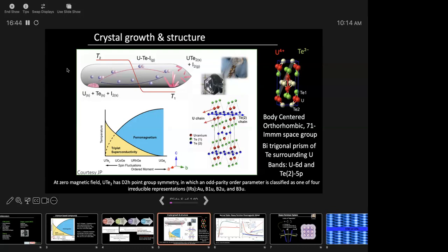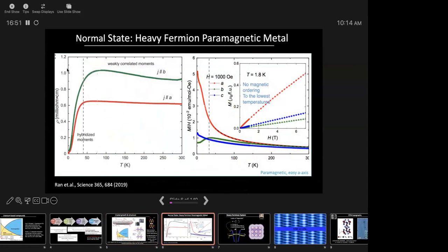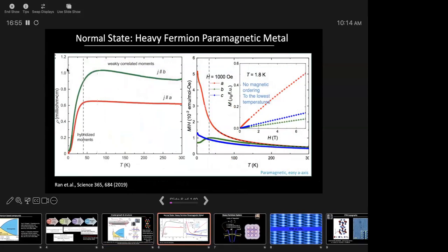So there's still a debate on what the order parameter actually is, and I'm not going to go into that right now. The normal state, like I said, is the heavy fermion, and you can see that from the resistivity. Resistivity is metallic, but resistivity goes up as temperature goes down. This is because of the increasing spin-spin interactions. And once the Kondo coherence temperature is reached, then resistivity plummets. So this is the signature of heavy fermion physics. This is susceptibility, and the a-axis, this red curve, is the easy axis. You can see that there's no magnetic ordering down to the lowest temperatures, so that's that.